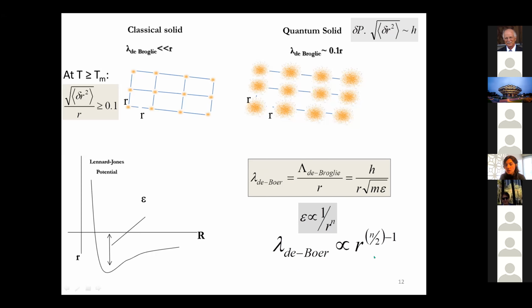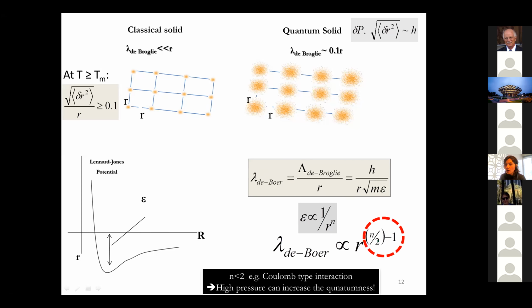Now, if you look at this equation closely, you can see that if n over 2 minus 1 is less than 0, this exponent is negative. And as we increase the pressure, R goes down and the de Boer parameter in that case goes up. So that is the case for n less than 2, where we have long range interaction, something like a Coulomb type interaction where n is roughly 1. But if you have short range interactions like van der Waals materials, where n is very large, then this exponent is positive. And as you increase the pressure, R is going to go down, and the de Boer parameter is going to diminish.